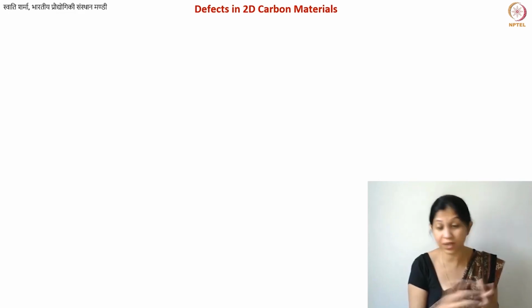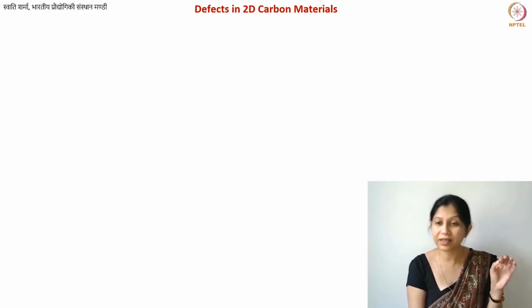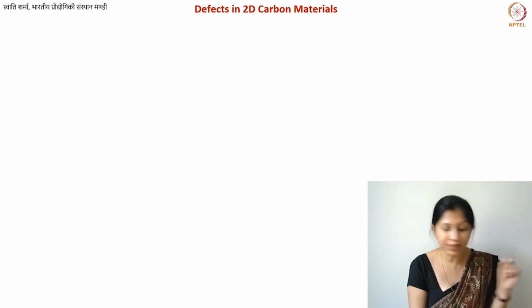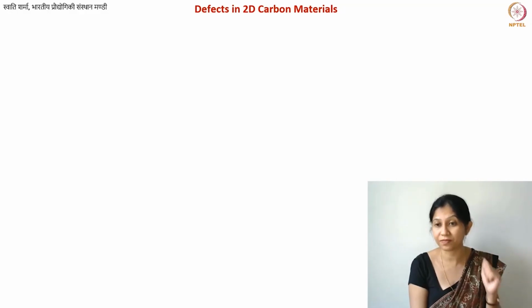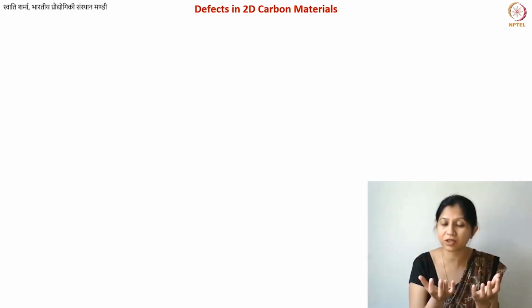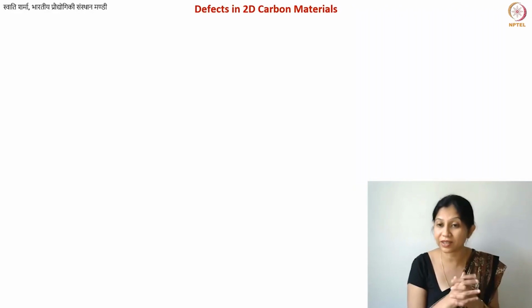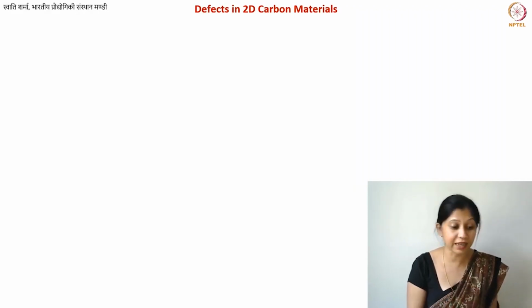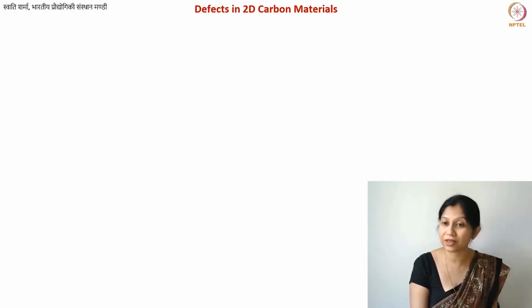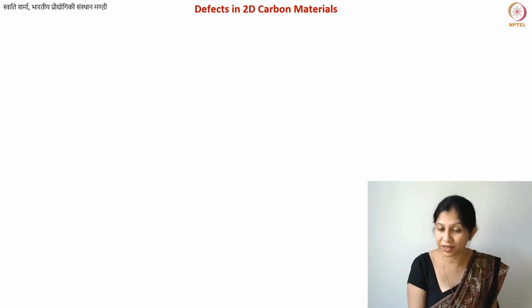in that case, especially for example, non-graphitizing carbons, then we know that there is a significant number of non-six-membered rings, and that is in fact responsible for the curvature. That is why we get these curved carbon structures. And when we have a very high curvature, we also sometimes get completely closed structures, for example, fullerene-like structures, which result in the closed porosity of these materials. So we know that the six-membered sheets can also contain non-six-membered rings here and there.